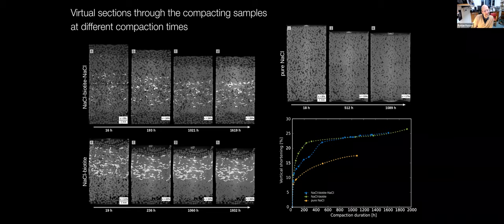You can see over time these samples get shorter, the distance between the glass beads here gets smaller. You can actually track individual biotite grains in there and see how they compact. I'm going to show you more of that in a second. And the other interesting bit is the darkest phase in there, the dark gray, that's brine-filled porosity. That porosity disappears, most obviously so in this specimen here. And there's no more porosity left in the end.